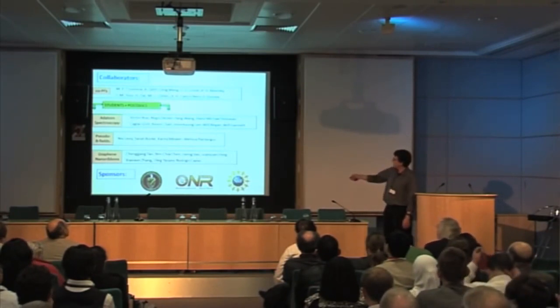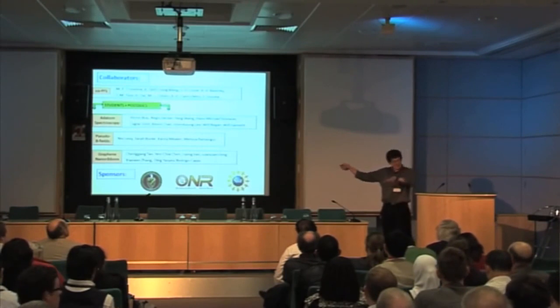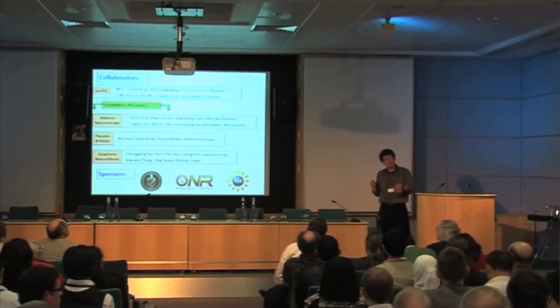And part of the problem is that the system where I'm doing the ad atom, the atomic manipulation of the atoms, that's the same system that I would use for the spin polarized STM. So we want to finish up that project before we do the spin polarized. Because it depends on the anisotropy energy. I do not expect a strong high anisotropy energy for the cobalt. And this is at 4 degrees Kelvin.